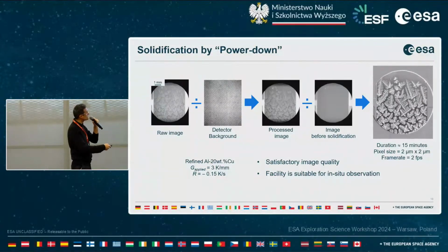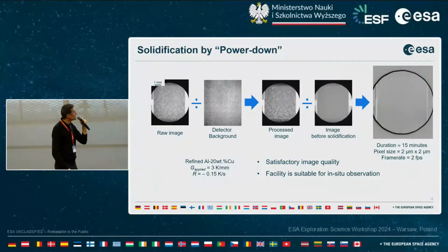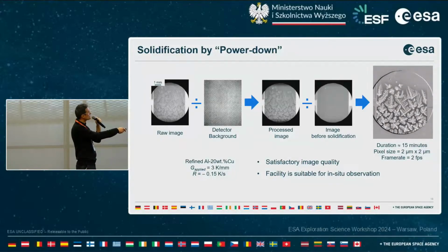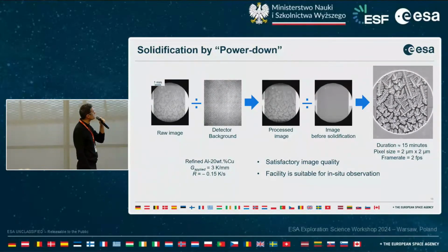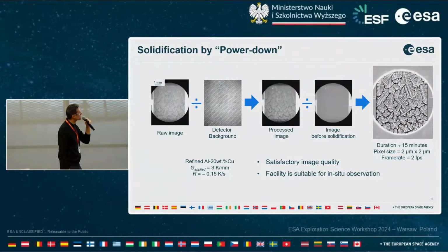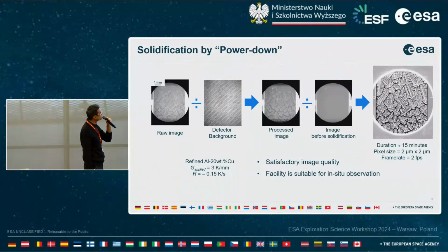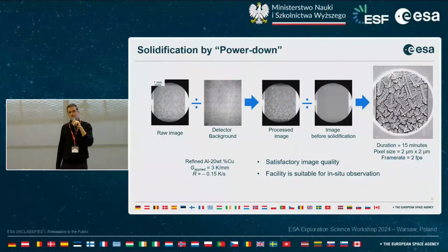It's a bit accelerated. The experiment actually lasted 15 minutes, but we can clearly see the directional solidification and the formation of the grains in this aluminum 20% copper alloy that was refined. I do not know if it's clear at the very end, but maybe you can see a dark shadow coming from the bottom, which is the solidification of the eutectic front that we will use to characterize the temperature field of the furnace in the field of view.